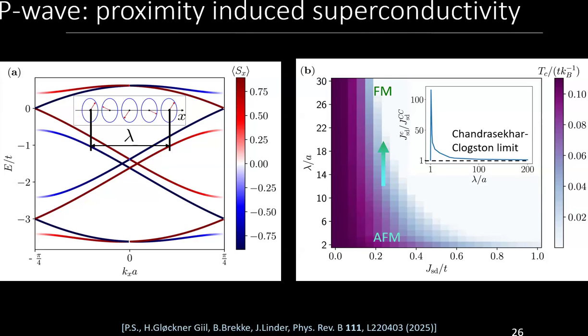But here, in a larger view, we see a long chain which looks like an almost homogeneous spin configuration on the length scale of the size of the Cooper pair. So essentially the Cooper pair lives in a magnetic field. It tries to break the spin singlet pair and orient spins in the same direction, while spin singlet superconductivity has spins pointing in opposite directions.